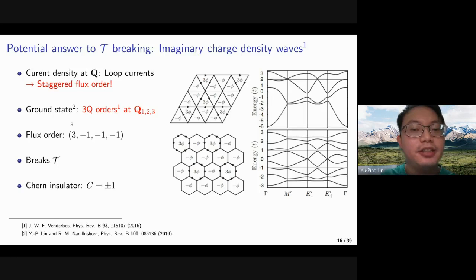And the ground state of these staggered flux orders will be the 3Q orders, which is similar to the previously proposed density waves. If we look at the flux order, there will be a 3, -1, -1, -1 structure. And similarly for the honeycomb lattice, 3, -1, -1, -1. Because there are currents in the lattice, if we apply time reversal, the current direction is reversed. So it breaks the time reversal symmetry.